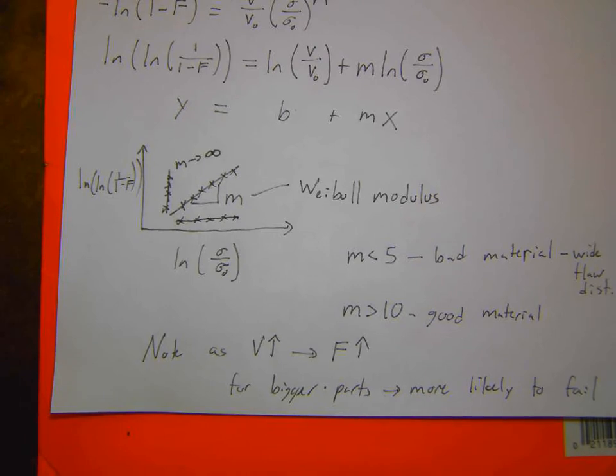And so we had kind of postulated that there was this idea of Weibull strengthening of materials. So we tested out these materials, and we saw very high strengths to failure for them. And we postulated that it was because of this idea of a Weibull distribution of strength for brittle materials, and that we were actually somewhere below this critical transition where you're getting to the theoretical strength of the materials. And a couple of years after we did that, this article was published showing experimentally, yeah, you are. You're getting toward that theoretical strength of the materials.